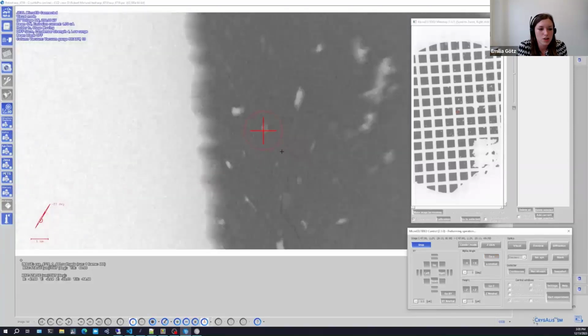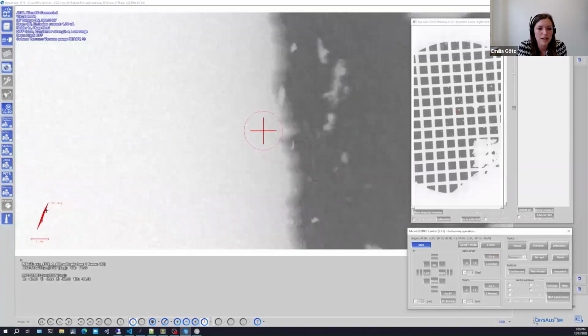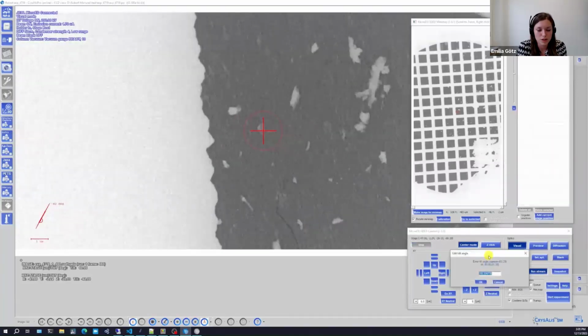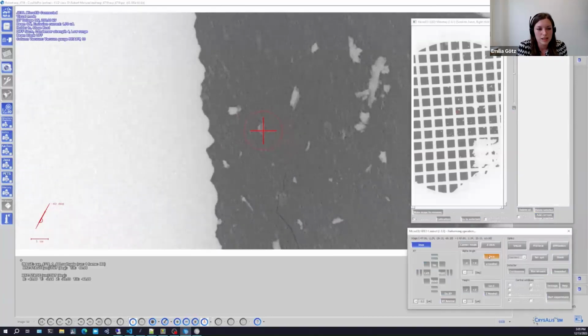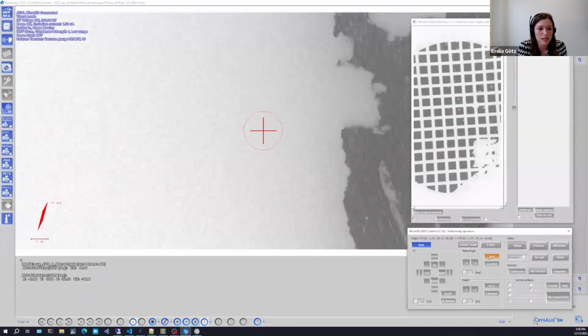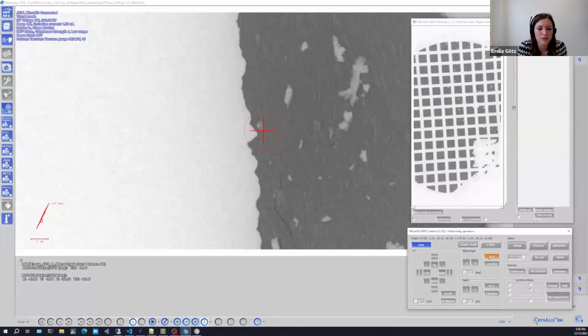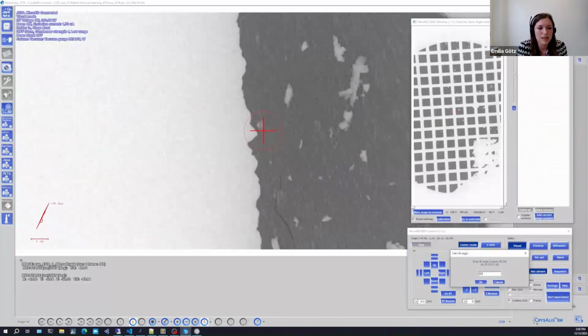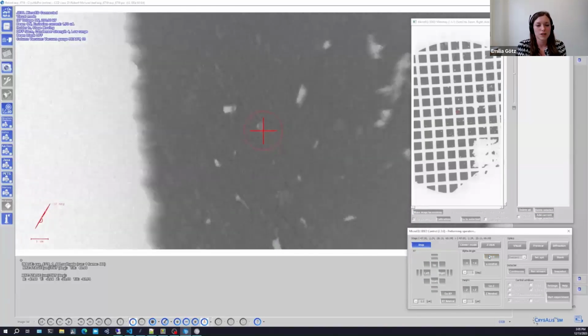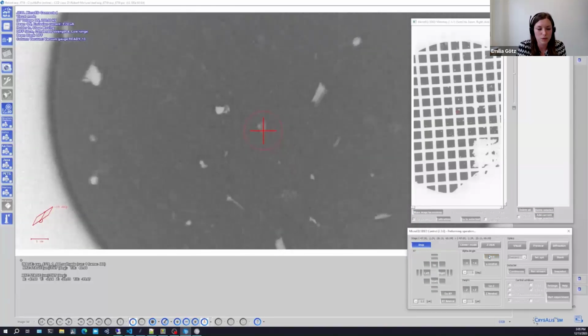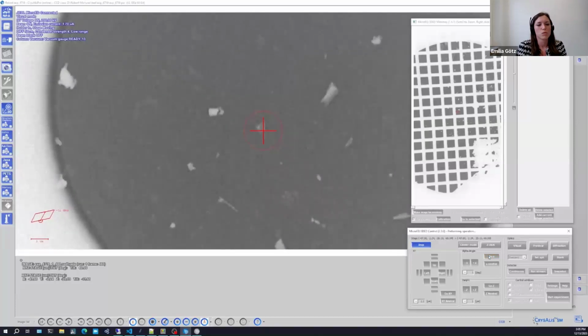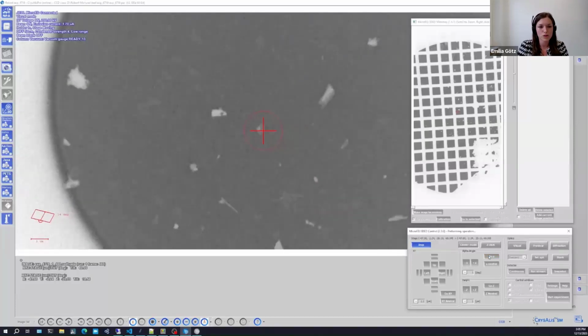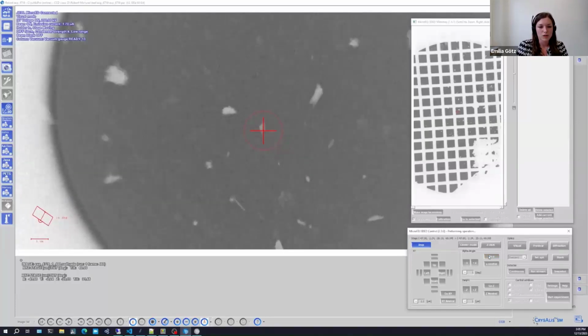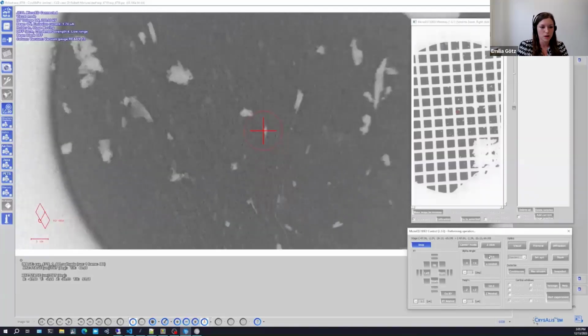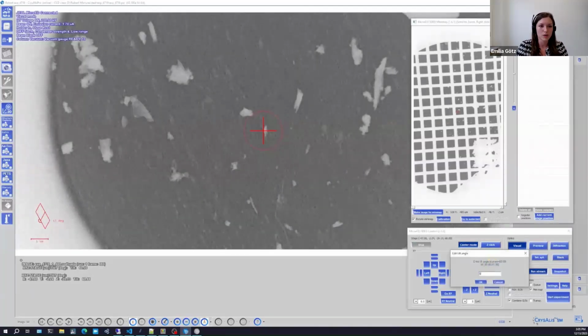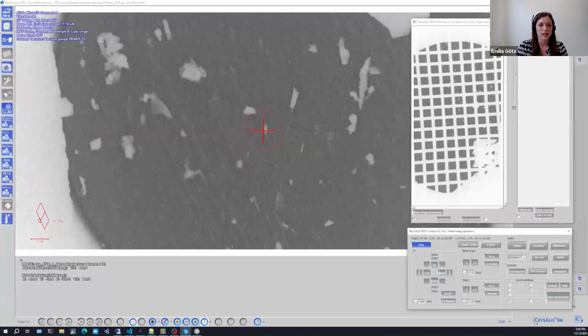And during the rotation, the crystal should always remain within the red circle that is shown in the middle, since this is the size of the selected area aperture and thus the area from which we will get the diffraction information. This means that the area from which we receive the diffraction information is not the field of view that we can see here in visual mode, but it's much smaller and more defined. So once we have figured out the scan range from negative to positive and go as far as we can, we then set up the data collection.